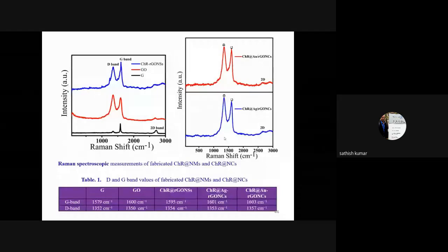Here we can see based on their intensities. The increased intensity clearly indicates the conversion of multi-layer graphite into single layer graphene oxide and reduced graphene oxide. And the disappearance of the 2D band clearly indicates the conversion of graphite into reduced graphene oxide. Similarly, for the metal decorated nanosheets, the nanocomposites show increased intensity due to the optical property of the silver and gold nanoparticles, and also because of the surface plasmon resonance effect.